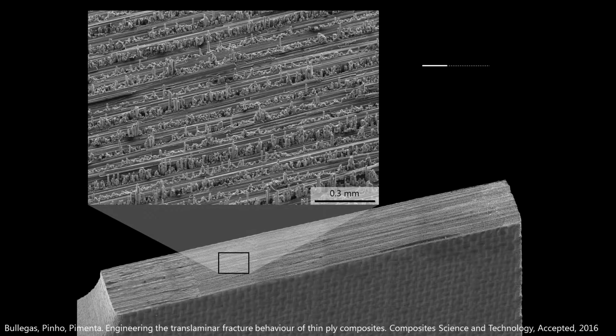So this is a standard unmodified carbon fiber composite with some 0-degree plies. It's the fibers that you see sticking out from the fracture surface, and some 90-degree plies where the fibers are running along the fracture surface. So if you look at this image, the people who know carbon fiber composites will look at this and think this is a very brittle behavior because the pull-out of the fibers is very small. If you look at that scale, those 0.3 millimeters, you can see that the fibers, which have about 5 micrometers in diameter, have a pull-out which is really just micrometers. So this is very brittle.